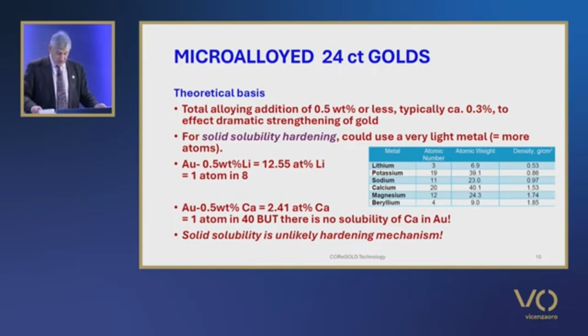Such small additions are approaching those values typically used to control grain size by grain refiners, such as cobalt or iridium in carat golds. As gold is a low stacking fault metal, and stacking faults are a type of crystal lattice defect, control of grain size alone or in combination with cold work will not yield significant hardening in pure gold. So such small additions cannot work through grain size control only.